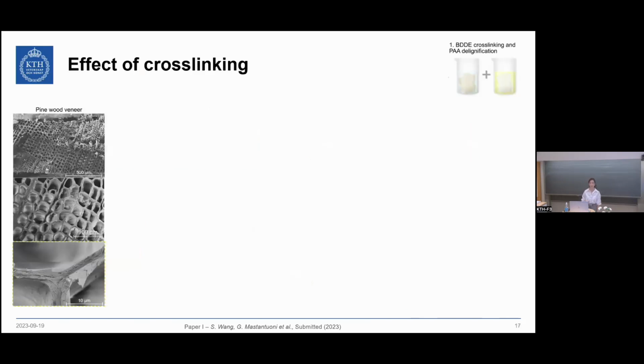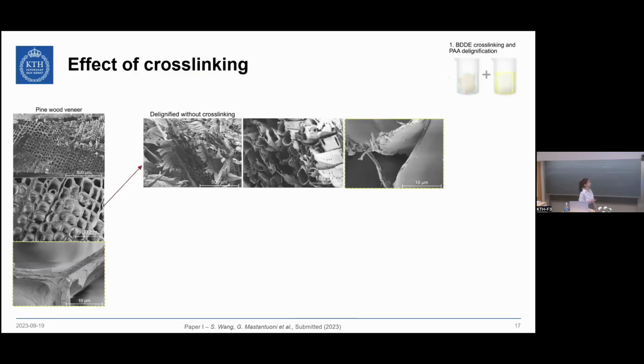First of all, we can see what happens when we cross-link the material. This is the microstructure of native wood. You can see the cellular arrangement as well as a very dense middle lamella. If we delignify the material without first improving the cohesion, the fibers are barely holding together, and the middle lamella region looks almost completely eroded. This means that this material tends to fall apart into individual fibers.